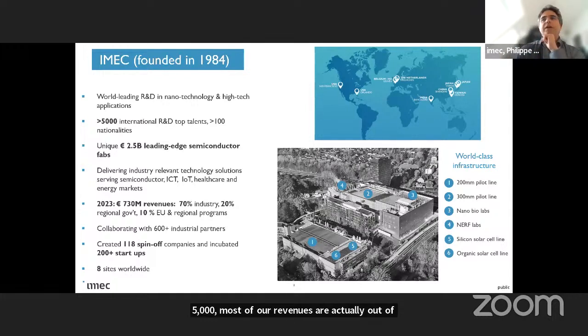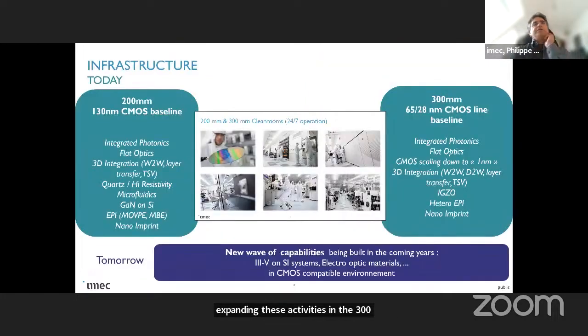And we have two sites, one on 200 millimeter, one on 300 millimeter, and the 200 millimeter site is more dedicated to the most mature activities, including photonics and optics. But we are also expanding these activities in the 300 millimeter. So the infrastructure that we have on the 200 millimeter is originally based on a CMOS baseline 0.13. The 300 millimeter is more advanced, 65 to 28. We are, of course, well known to other people for the most advanced CMOS scaling, but I didn't put it on this slide. We operate 24/7, and we have all kinds of integrated photonics and flat optics technology, together with the ability to manipulate different kinds of substrates such as glass substrates.